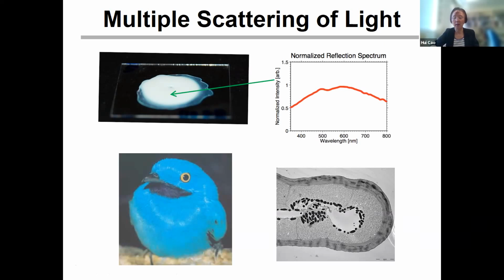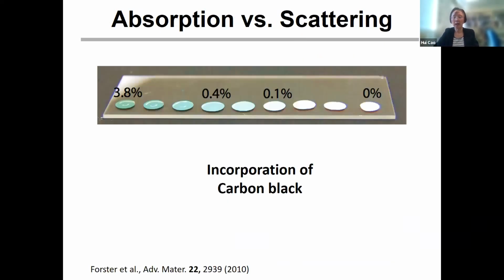So now we say, okay, we learn from birds. Let's do that too. We have this solution of two different sizes of polystyrene spheres. Now we're adding some carbon black. It's carbon black nanoparticles, just like ink, right? And those carbon black nanoparticles have a broadband absorption, so they can absorb all colors. So we gradually increase the concentration of the carbon black nanoparticles, and then do the drop casting. Now you see that when the concentration is higher, we start to see the color come up, right? We initially have white. Then for the same thickness, we can start to see the green-blue color appear.